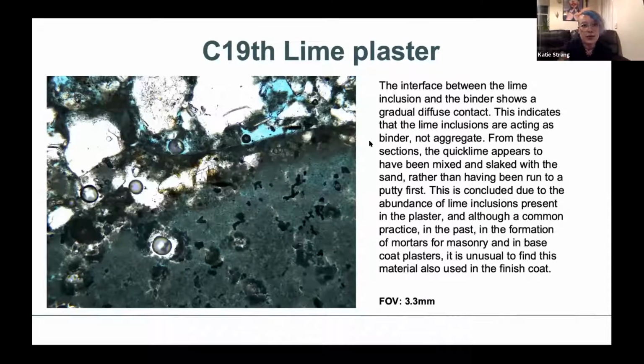And this is another image of the lime inclusion, where it's acting as part of the binder and not the aggregate. And from the sections, we think it was prepared as a quicklime initially, which is basically where you add your water to your calcium oxide, but it seems that it has been left for a while before they've actually put it into the material. There are various ways that they can do this. Quite often, if you've got a dolomitic material, they might not have known that it was dolomite, but they would know that it behaved differently to their typical mortars. So we do have historical evidence of people taking these precautions when they're using dolomitic lime, but in this instance, it just seems like they were unaware of what they were actually using as a material.